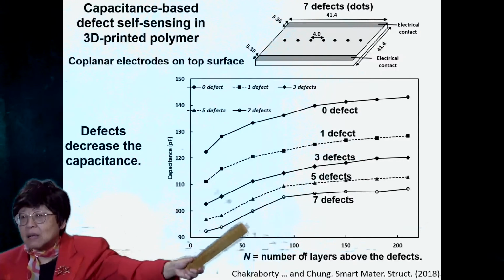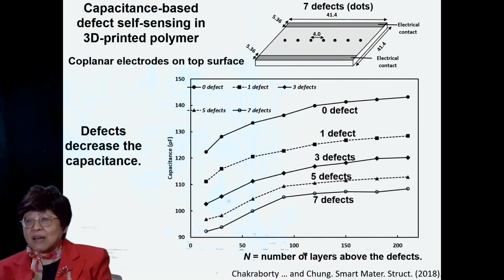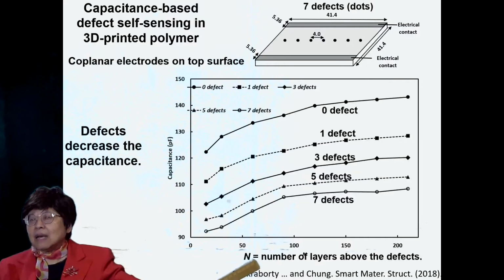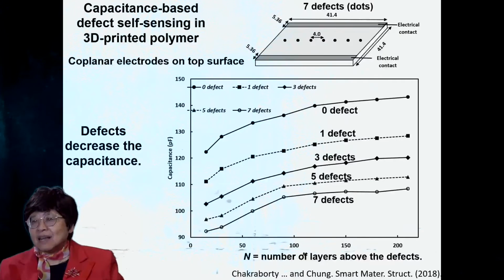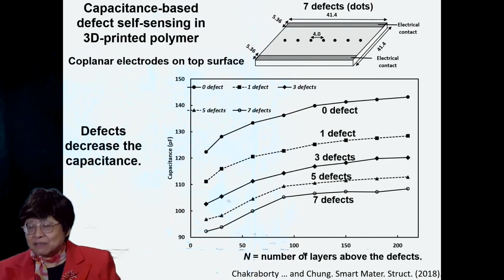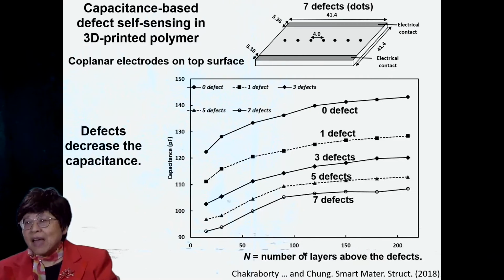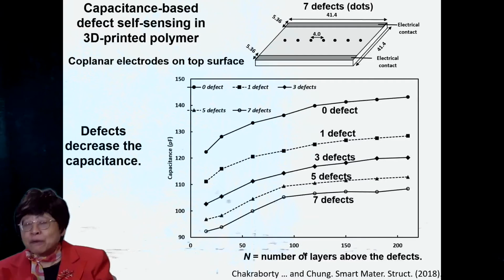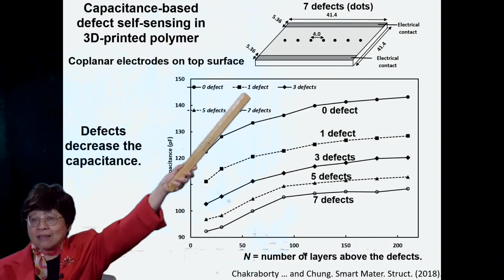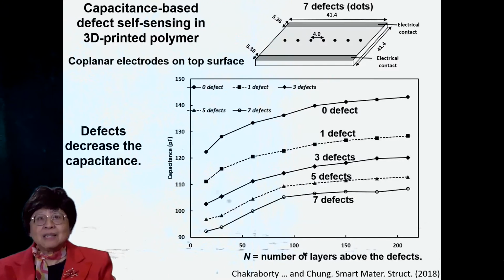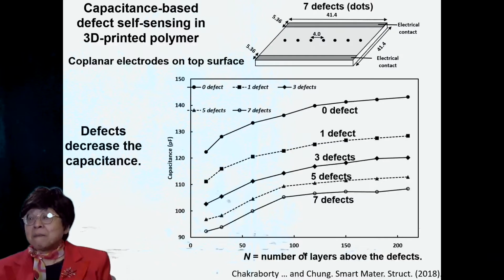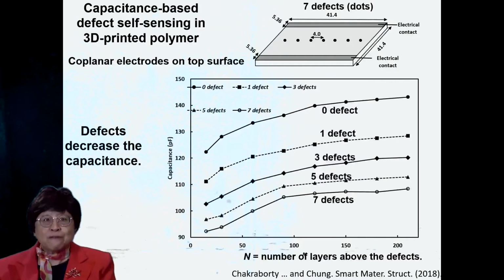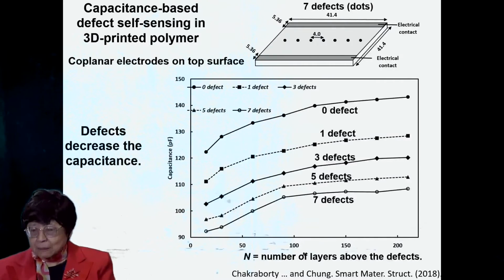The more is the defects, the lower is the capacitance, because the defects intersect the electric field lines again, thus decreasing the capacitance. And note that the more is N, the higher is the capacitance, meaning that the sensing is less sensitive. Just because the bigger N means there are more layers above the defect, and the electrodes are at the very top. So the sensitivity for sensing those defects would be less. So we are able to relate the capacitance to both the number of defects and where the defect locates.